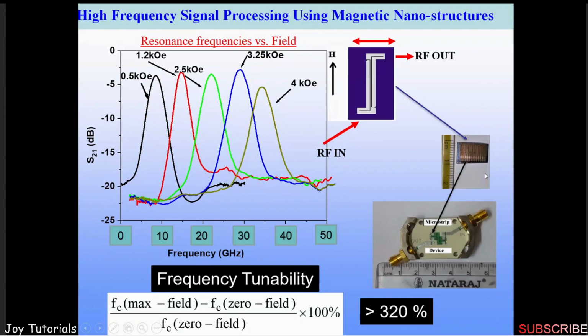After designing these devices, we put them in a casing unit. Then by using the wire bonder, we bond this device between the input and output connecting devices to the network analyzer. What we saw is that this device has a frequency tunability, that is, the difference between the frequency at the maximum field and at zero field, divided by the zero-field frequency, times 100%, is 300%. It is a huge range, starting from 8 gigahertz and going towards something like 35 gigahertz. But having a magnet near a device is not a very good thing.